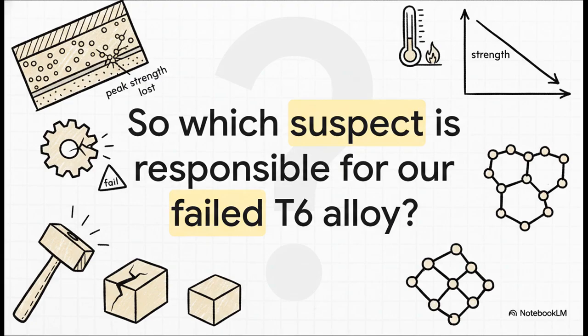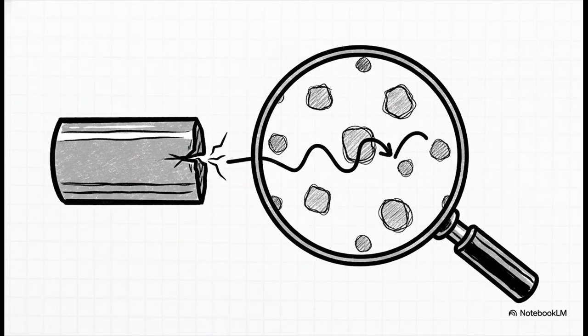So which one is it? Let's think this through. A part that was engineered for peak strength, it wouldn't fail because it wasn't strong enough yet, right? No. It would fail because the strength it was supposed to have had somehow disappeared. And the verdict is overaging. The alloy was cooked for too long. By holding it at that aging temperature past the perfect peak point, the entire internal strengthening architecture was compromised. Those beautiful, coherent structures that acted as perfect roadblocks, they dissolved and reformed into big, clunky, incoherent particles that the dislocations can just easily go around. The material got soft, it got weak, and that led directly to a catastrophic failure.